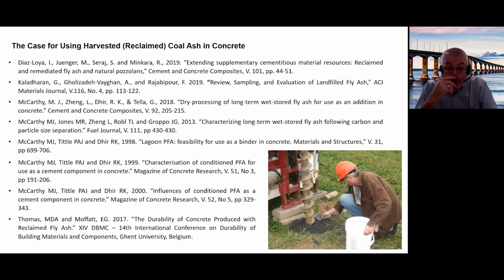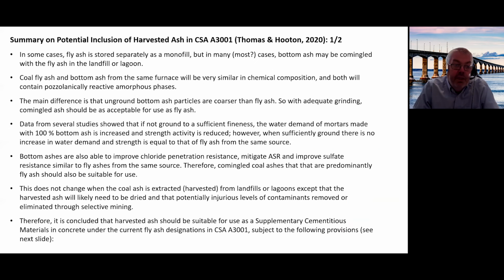A lot of the material in lagoons and landfills is suitable for use with, in some cases, a minimum amount of processing. Some processing is obviously going to be required. I've deliberately used the term coal ash here rather than fly ash because very often fly ash is disposed of together with bottom ash. You commingle them together in a disposal site, and then you have to consider it as coal ash. It's neither fly ash nor bottom ash, it's both. So hence the term coal ash.